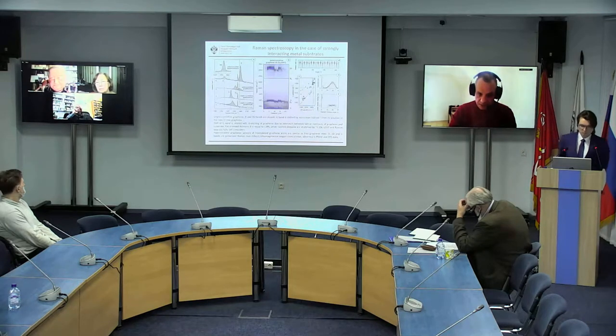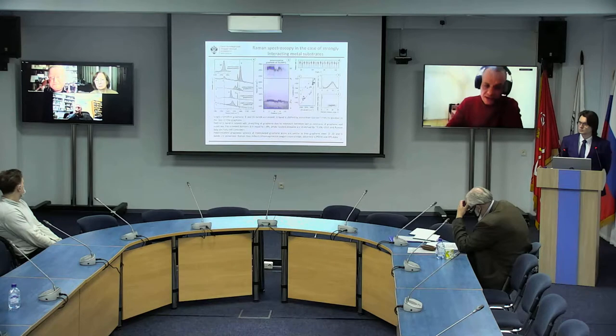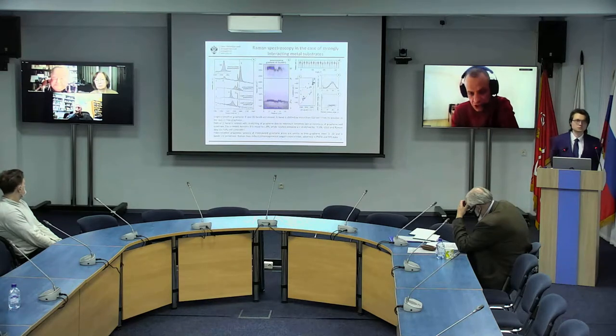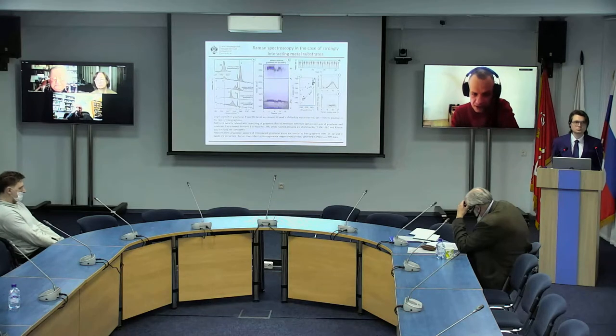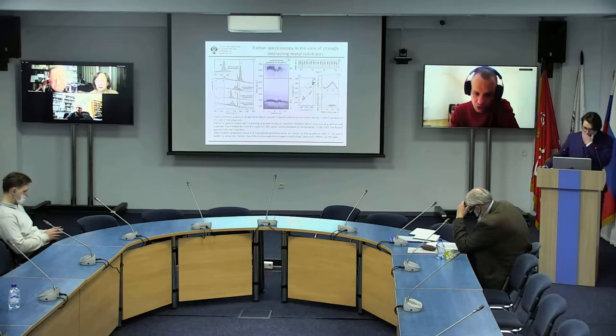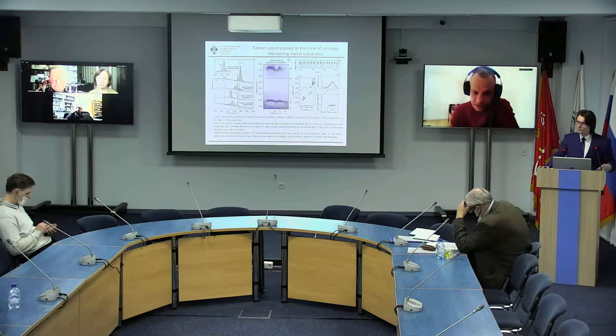So then I go down the thesis, and what I find interesting is that he studies this recrystallization. He starts with polycrystalline graphene, and then he essentially heats it. He looks at the intensity of the diffraction spots due to the disoriented domains, and he records this intensity as a function of annealing time, and he gets quite a good fit with the Kolmogorov-Johnson-Mehl-Avrami model. He has some fit parameters there that probably depend on the dimensionality and on the activation energy, that I also have questions for.